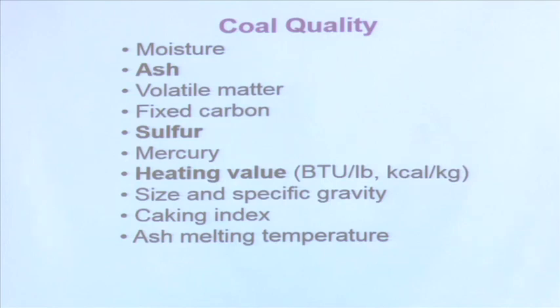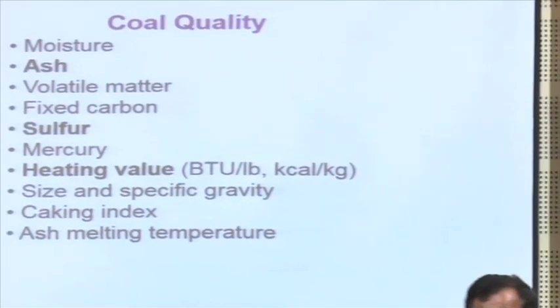That is also the problem with US coal, but in US coal most of the sulfur comes from pyrite, that is a mineral, FeS2. But in our northeast region coal, the sulfur is mostly organic sulfur, and this organic sulfur is distributed along the matrix of the coal. So, it has to be ground to very fine sizes, which makes the entire process not economically viable at this moment. So, here there is a research problem for you, which I am not inventing, it is there already, I am just mentioning it. If you can solve it.